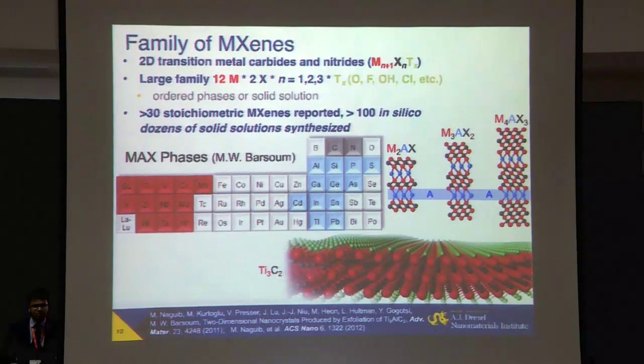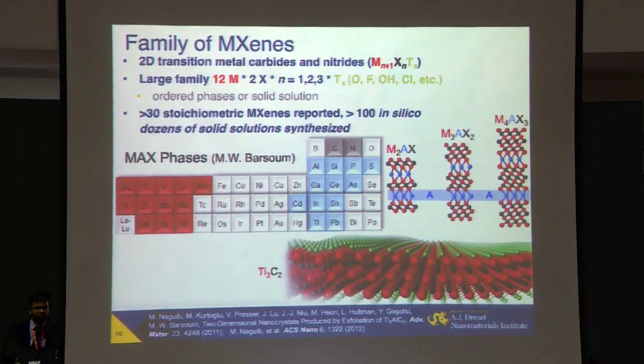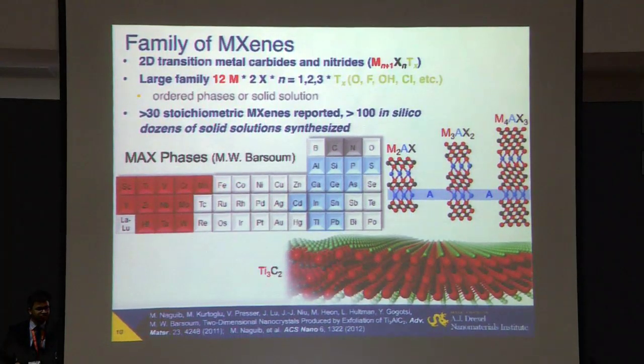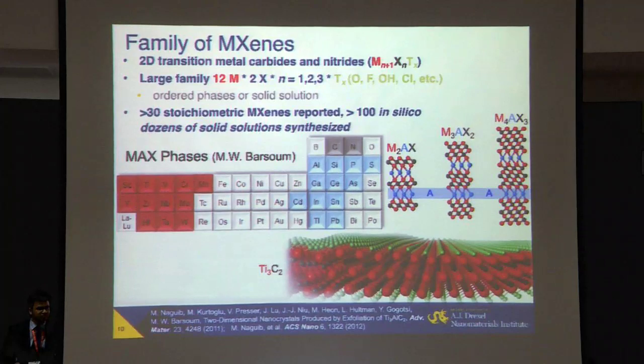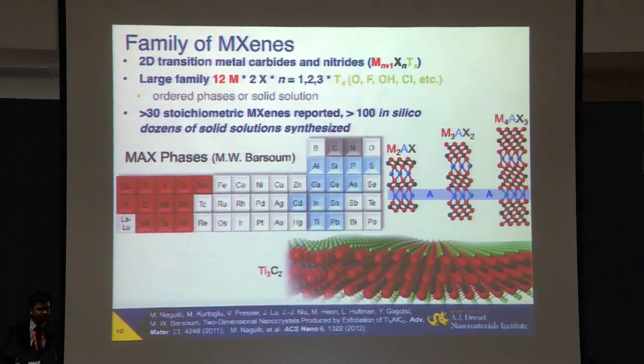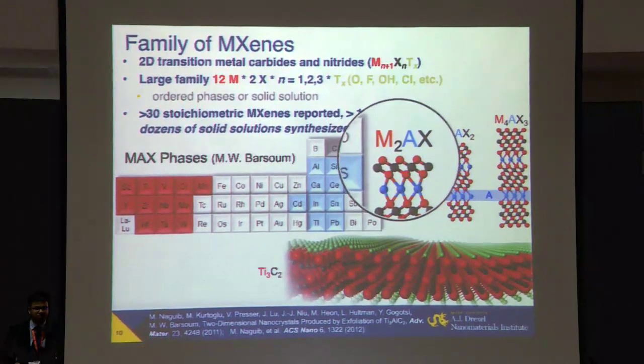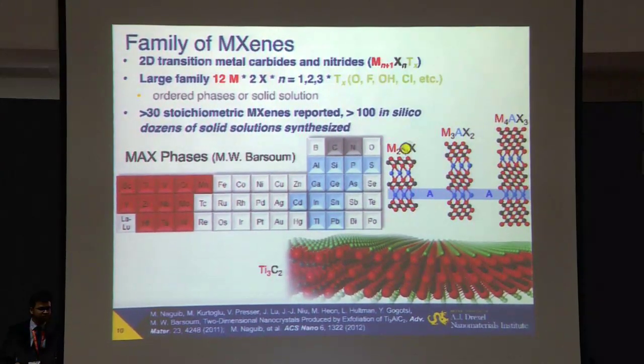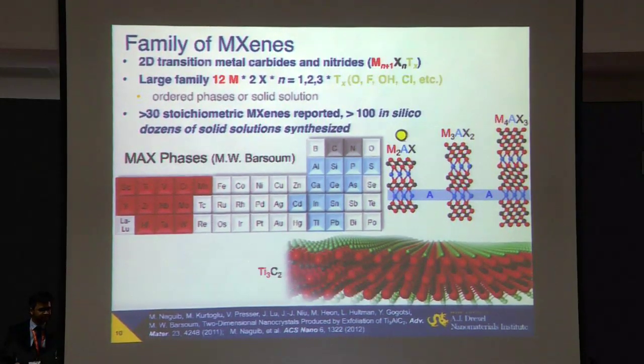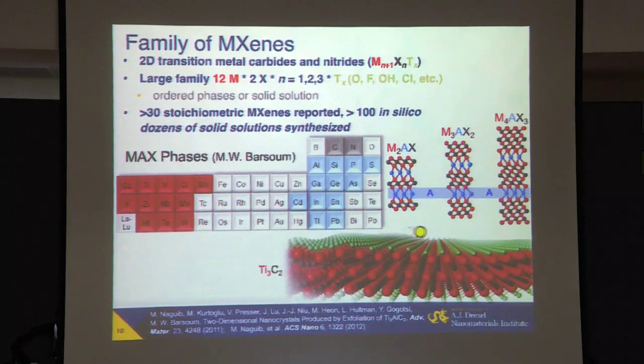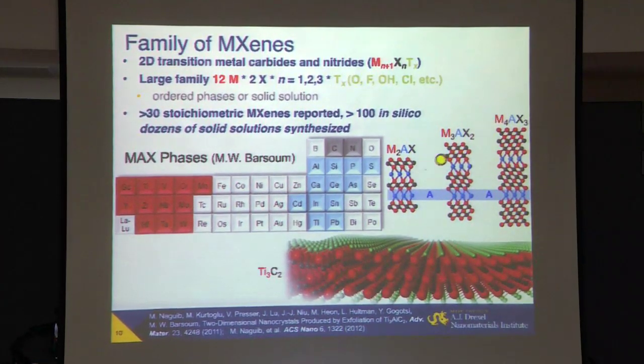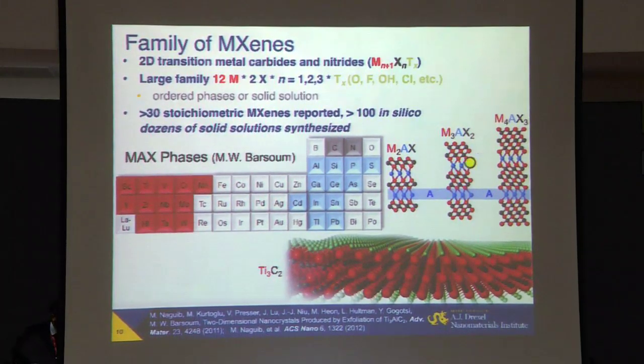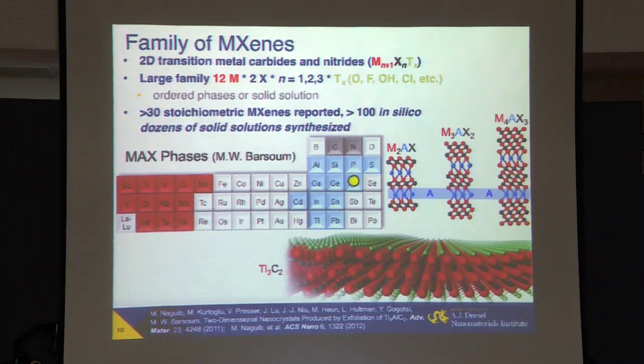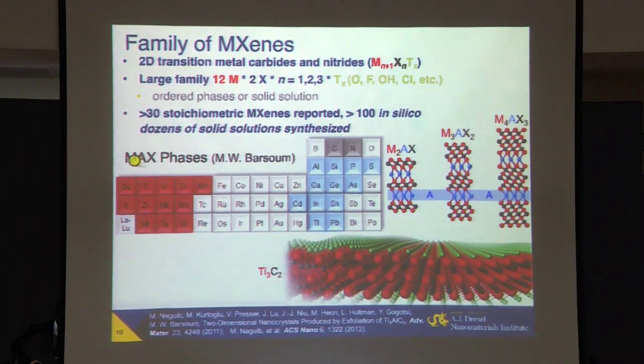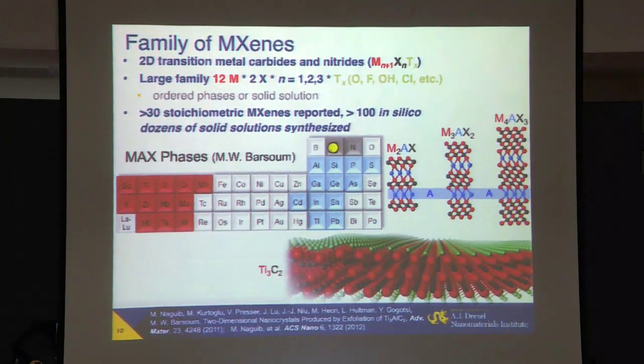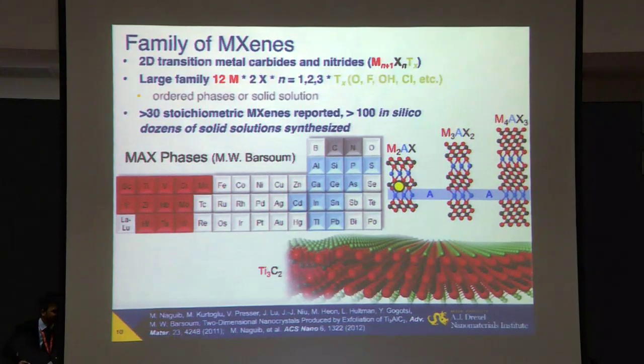So, those materials have this wealth of attractive properties. How do we make them? That's, again, very important because some materials can be made, but only as nanomaterials in nano quantities, and this is not enough for technology usually. So we actually take a ceramic material that Professor Barsoum, my colleague at Drexel University, discovered, or he really did not discover it. They were discovered by Nowotny and others in the 1960s, but he developed them as a field of materials. Those are materials made of layers of carbide, mono, double, triple layer, separated by a layer of these blue atoms, which are the A element. They're called MAX phases. So M elements are elements of this red one that we use in MXene, X is carbon or nitrogen, and this blue are atoms of the A element.